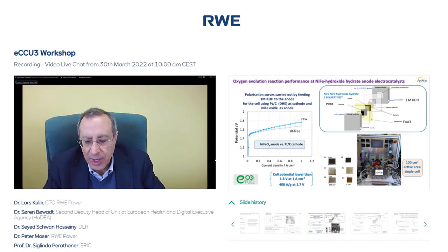So now regarding the oxygen evolution reaction in a practical device in a zero gap cell, using platinum at the cathode as a counter and reference electrode, we can achieve at 1 ampere per square centimeter 1.8 or 1.7 volts, 1.8 in the raw curve, 1.7 volts in the IR free curve, that will correspond to a voltage efficiency for the anode much better than 80%.